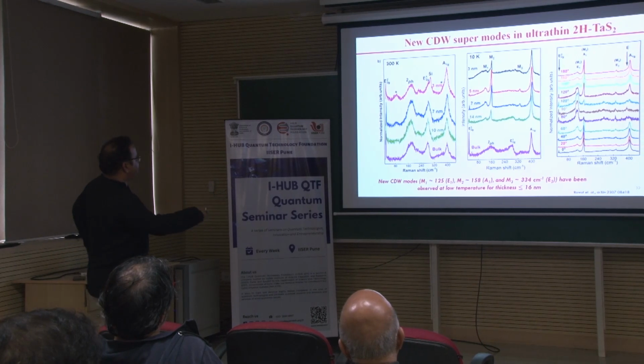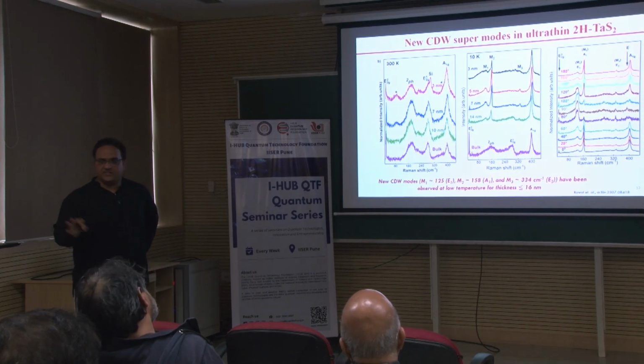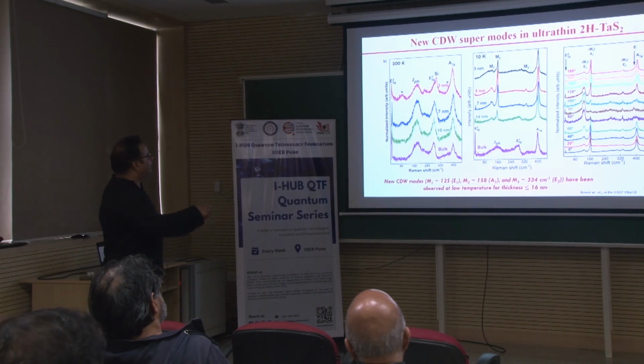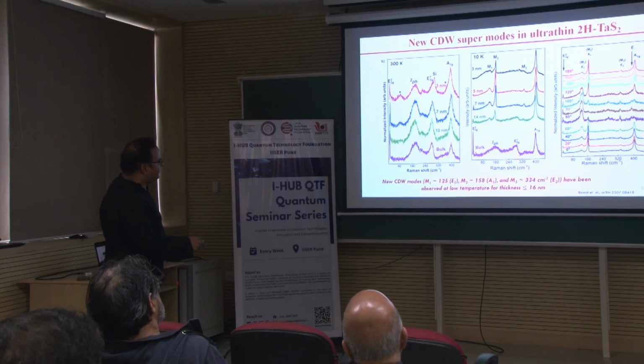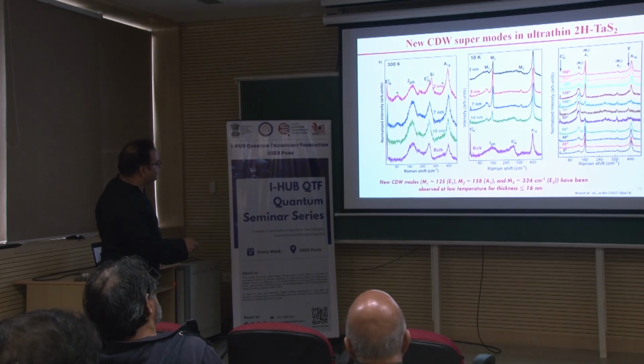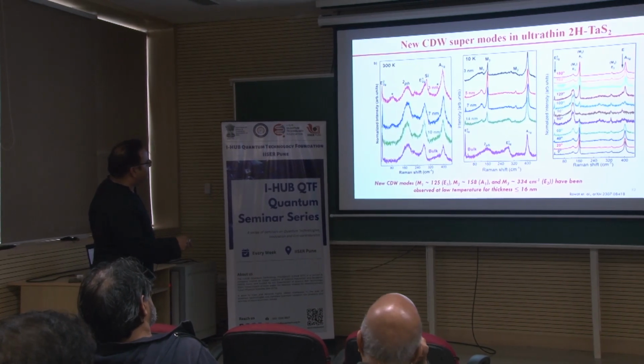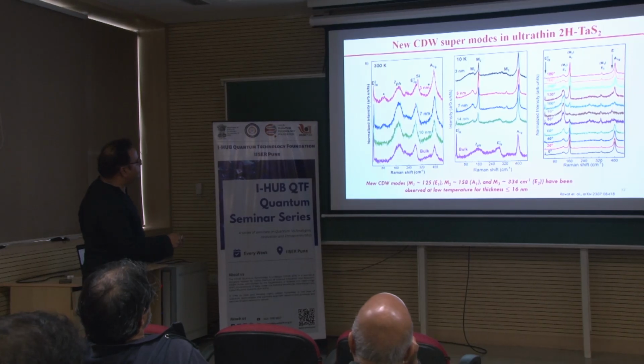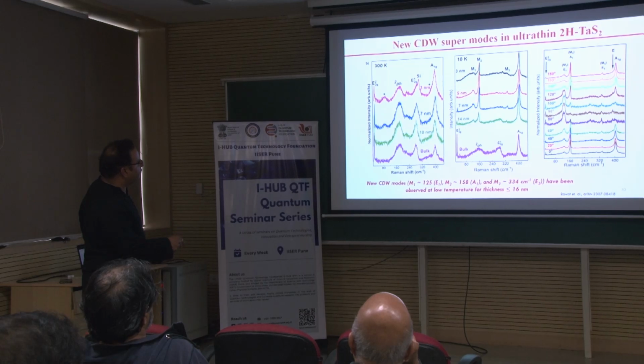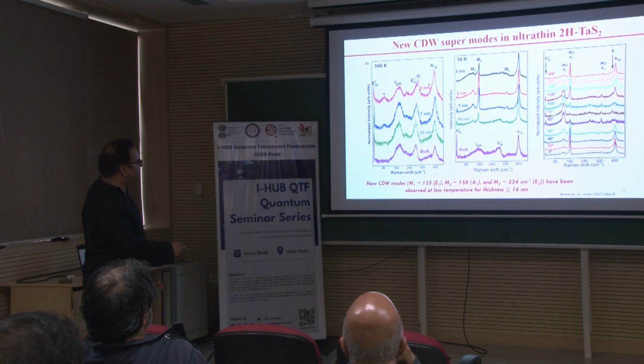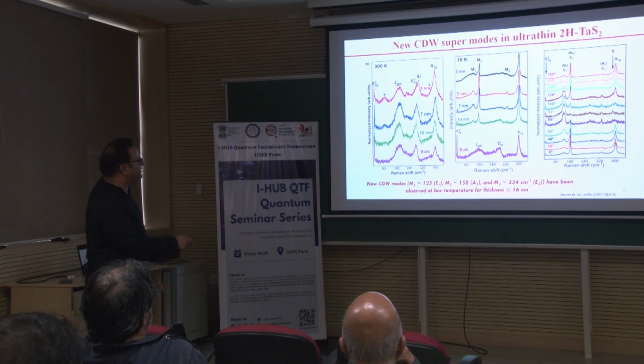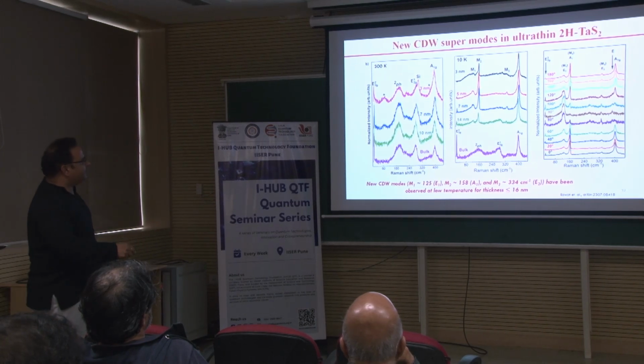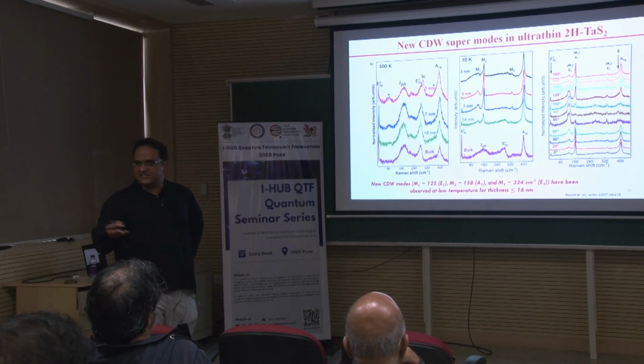At room temperature, none of these are showing any kind of signature of charge density wave. At 10 Kelvin, this is the bulk, you have seen that the A1g mode is there, and a very feeble mode here at 14 nanometer and 7 nanometer. You have some modes coming up, called M1 and M2. Look at the vertical axis here, this is the A1g mode, and there is another M3 mode here, and this is the usual AG mode. We have done the polarization to find out the symmetries of these modes.